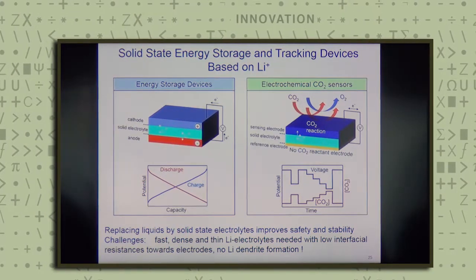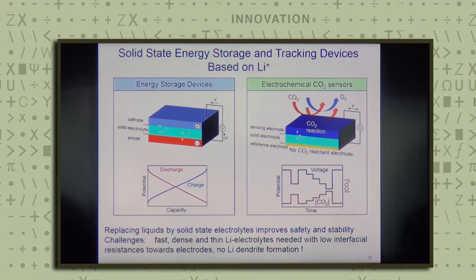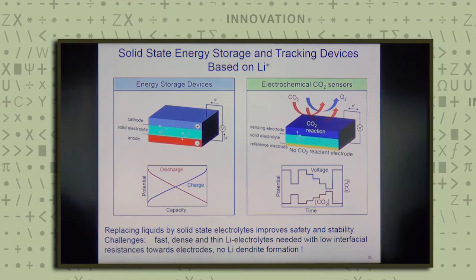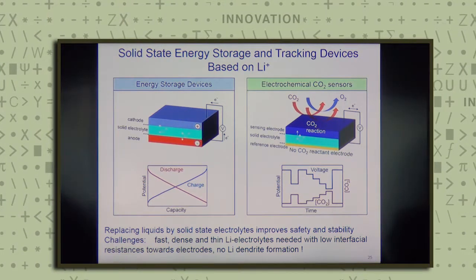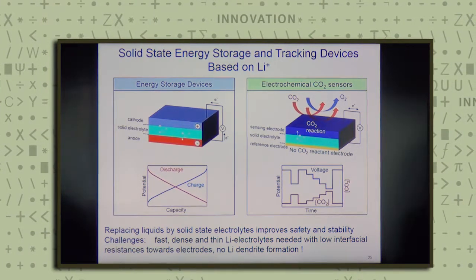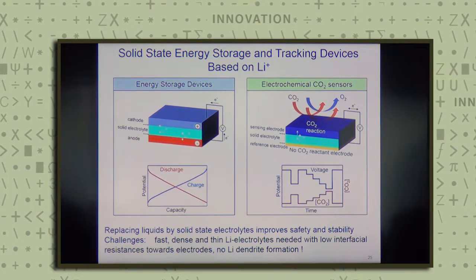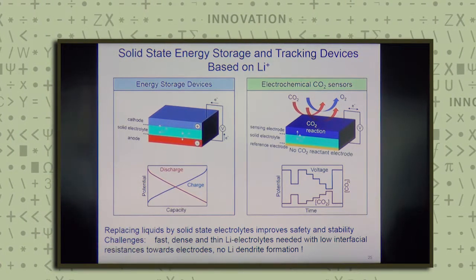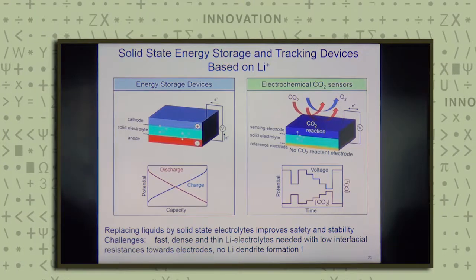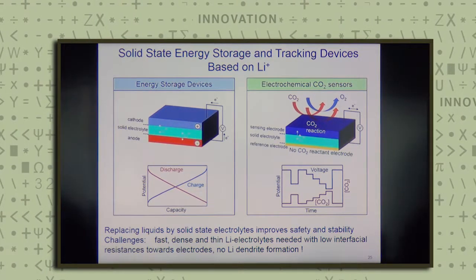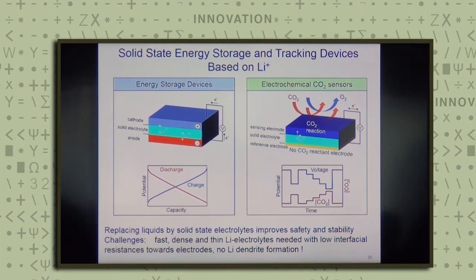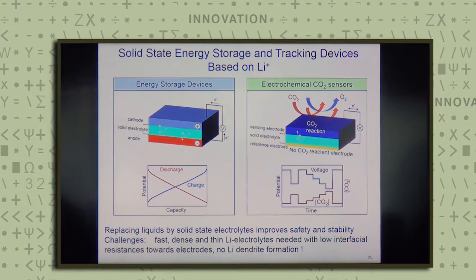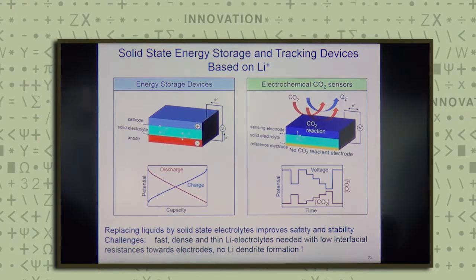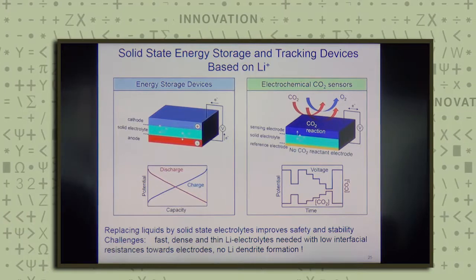What you can do is use the battery technology and not create a classic battery cell, but refunctionalize the electrodes so that you have a sensing electrode reacting, for instance, to carbon dioxide, and the other one being a reference electrode, for instance, gold. And you can measure an electrochemical potential that you can use to track carbon dioxide and other species. So in other words, you can use an electrolyte and create completely different functions than a battery just by putting other electrodes on top. Isn't that beautiful?